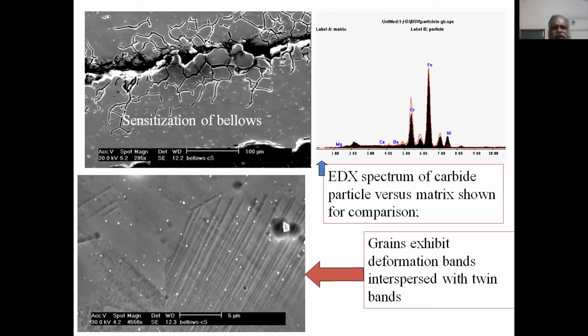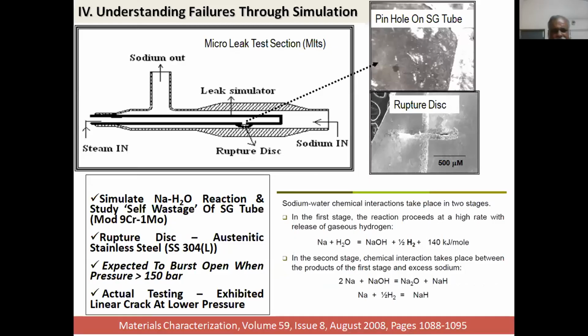And are you sure that this is so? Yes. If you look at the cross-sectional metallography, it clearly shows this interaction resulted in grains exhibiting deformation bands which are interspersed with twin bands, suggesting the huge amount of reaction that has happened, resulting in the failure. Let me go into a similar thing, which is again a simulation work. With this I would close.